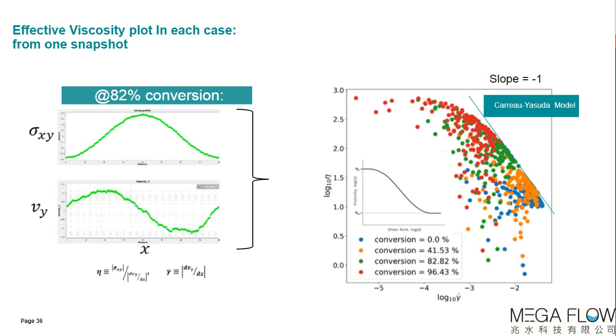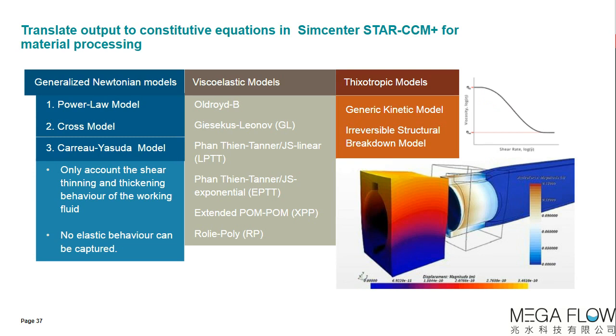Now here, this envelope is funny too. This envelope you see is actually the Carreau-Yasuda model. That model is in Star-CCM+, and also in other CFD packages, I must honestly say. But Star-CCM+ has that too. So look here, generalized Newtonian models. We have lots of models there, power law model, Cross models. And this is the one that we need, the Carreau-Yasuda model. It's an empirical model, completely empirical. There's no molecular motivation there. It just says, okay, when you have a low shear rate, you have a plateau. When you have a large shear rate, you have a plateau, but that plateau is lower because you have shear thinning, and let's just draw something in between. That's basically the Carreau-Yasuda model.